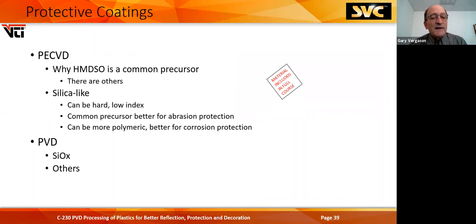Protective coatings, we talk about PECVD. HMDSO is the most common precursor used, and there are others. It's silica-like. It can be hard when you buffer it with some more oxygen, with low indexes. It can be more polymeric, better for corrosion protection. You can do SiO2, SiOx with PVD, a little more persnickety, a little harder to control. But everybody wants something that's the right color, the right thickness, and they want it to last forever and never be scratched. But remember, you're putting coatings on a plastic part. It's like an M&M. It's going to be only as good as the candy shell on the outside.